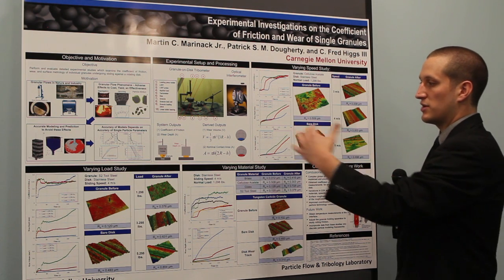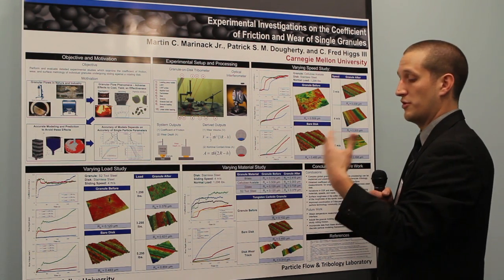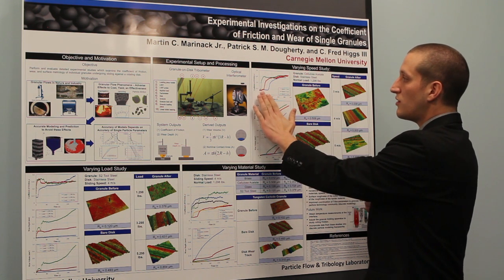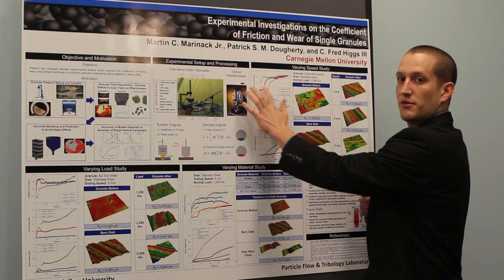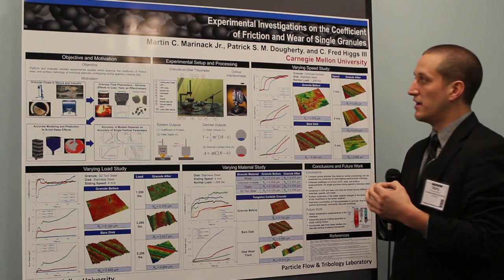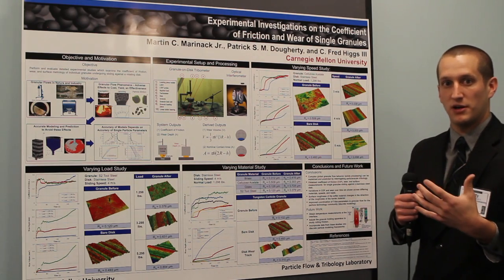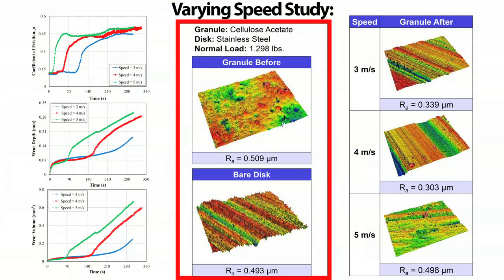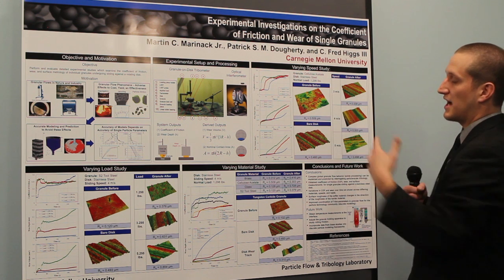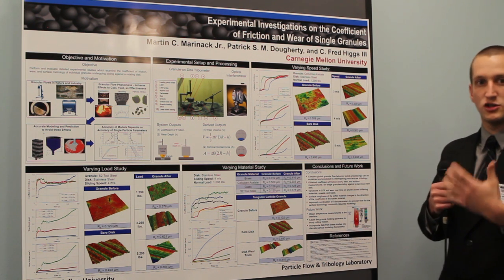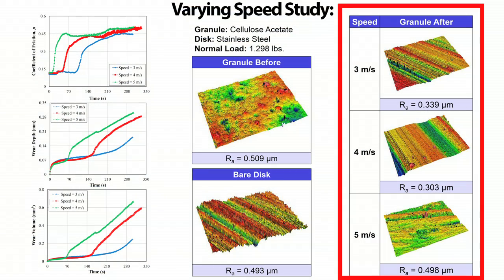What's interesting about this, if we go back to our motivation with the solids processing community, is that many of the particles in these rigs aren't undergoing more sliding than what is seen in this transient region. So this might be something important for modelers to incorporate, is that perhaps using this steady state friction value may not be correct. And what we see from the surface images here is that we have a granule with a roughness of about 0.5 microns, and the disc is similar, close to 0.5 microns. And what's interesting with the cellulose acetate material is that it actually deposits a transfer film on the disc. And so what we see with the granule in each of the sliding tests is that the roughness of the granule is actually decreasing as it slides against the disc, as it's almost being polished somewhat.